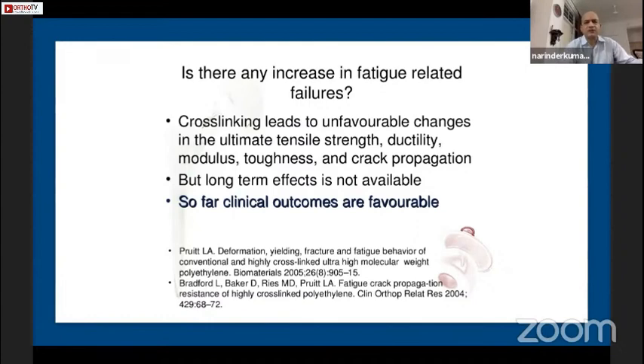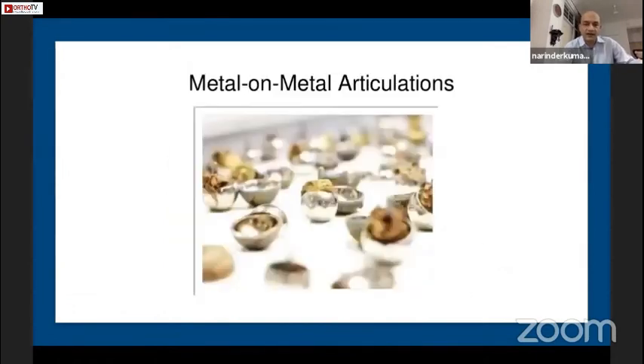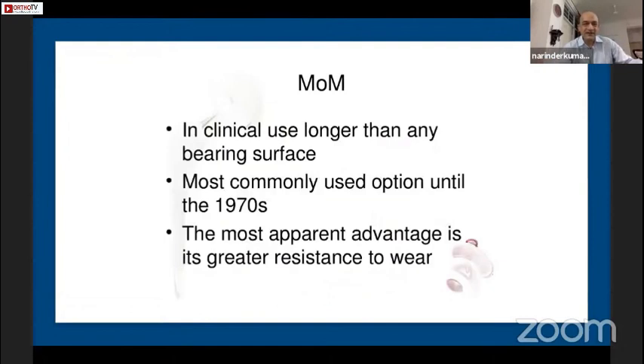But in the long term, we know that cross-linking has led to favorable as well as unfavorable changes, but so far clinical outcomes have been favorable. And that brings us to the metal-on-metal bearing, which is probably something which has been in clinical use much longer than any other bearing surface, much before the poly came along. McKee-Farrar used it and so many others used it.